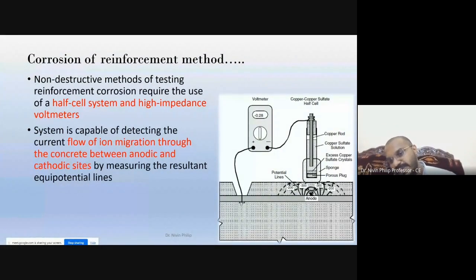One main point is that when we measure corrosion, we need a connection to the reinforcement. So the main difficulty in this method is that we have to establish a connection between the reinforcement and the meter. And this test is highly influenced by the moisture content. The surface should have moisture, and it should be equal in all areas. The moisture should not be different, otherwise the test will be influenced by a certain amount.